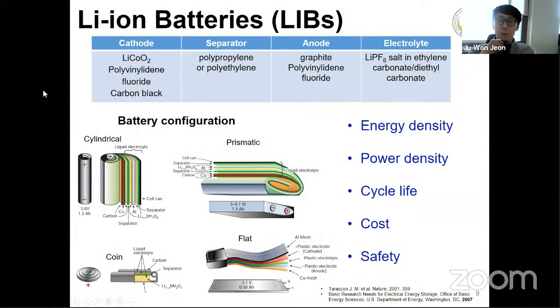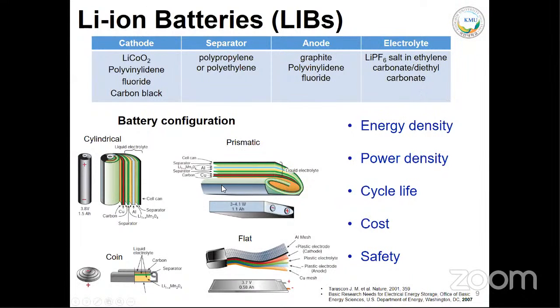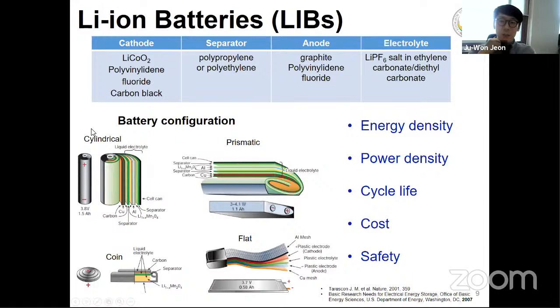The usual components of the lithium-ion battery are like this. For the cathode, a lithium cobalt oxide based material is used with a polymer binder like PVDF and conductive carbon black. For the anode, graphite with a binder is used, and the separator is a polypropylene and polyethylene porous structure, with an electrolyte of lithium salt in a carbonate-based solvent. The battery can be fabricated in various configurations like cylindrical, prismatic, coin, and flat type.